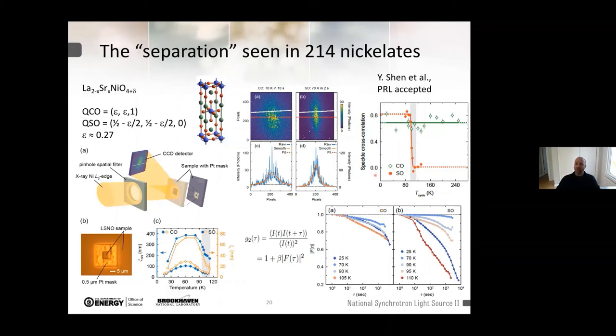And again, we can make a speckle cross-correlation as we did. And indeed, we see that the charge order stays, for example, constant, while the spin order evolves in a completely different way. We didn't go far enough to see that actually the charge order can also change, but there's more. Please follow the article because it's very rich in information. Let me just say that this is the intermediate scattering function, and this is the reason why before I plot g2 minus 1: what is left, apart from the contrast of the speckle, is indeed the dynamical evolution of the order, contained in this parameter.